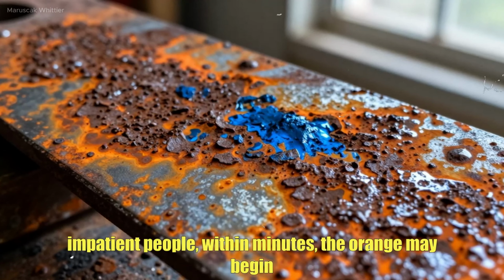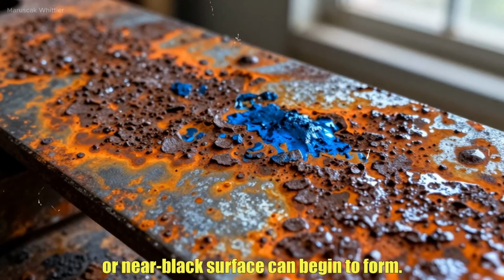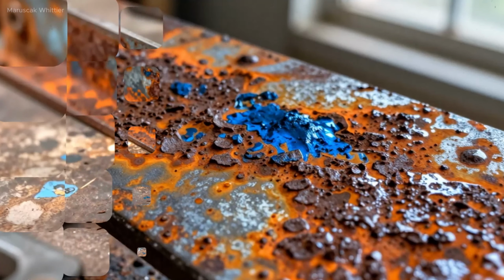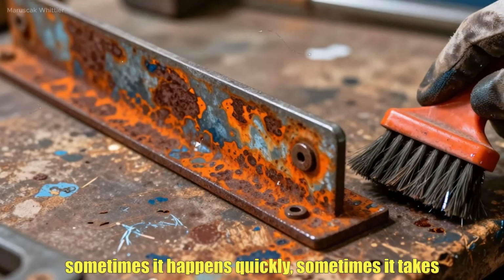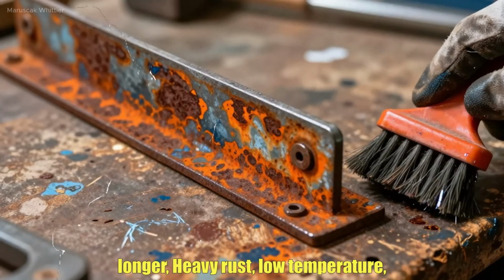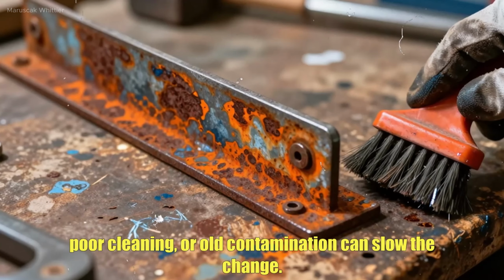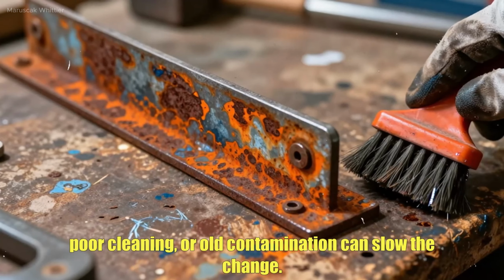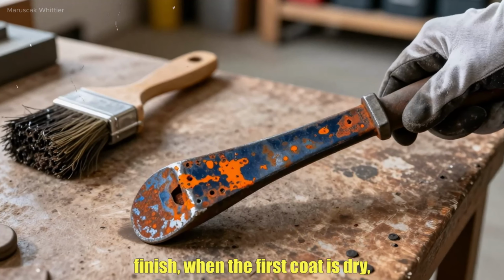Within minutes, the orange may begin to dull, then it may turn brown, then gray, then a blue-black or near-black surface can begin to form. Sometimes it happens quickly, sometimes it takes longer. Heavy rust, low temperature, poor cleaning, or old contamination can slow the change. Do not judge it after 2 minutes. Let the chemistry finish. When the first coat is dry, inspect it.